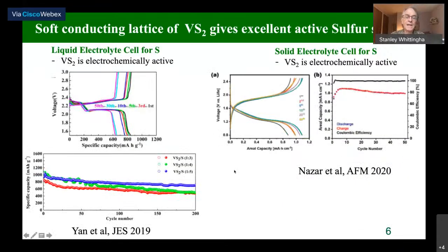Another use of these layered sulfides has come up recently, and this is as a support for sulfur and lithium sulfur cells. And I show you 2 examples. I won't go into any detail, but this on the left-hand side, this is using a liquid electrolyte, and you can see they're getting about 800 milliamp hours per gram. And this is quite stable. These are just 3 different ratios of vanadium disulfide to sulfur. So you can see again, the capacity is good and the cyclability is good.